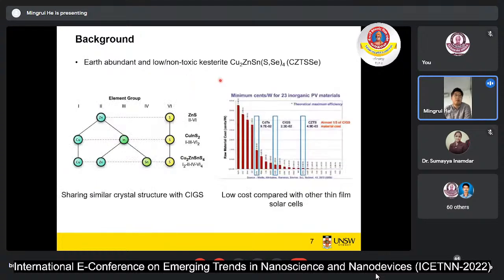So there is another material called kesterite, which is a copper zinc tin sulfur selenide compound. This compound also enjoys the advantage of being abundant and low or non-toxic. Because the selenide is a little bit toxic, a few groups remove the selenide and do only the pure sulfide CZTS. Our group initially focused only on the pure sulfide CZTS, but recently we have also developed the selenide-containing kesterite solar cell.